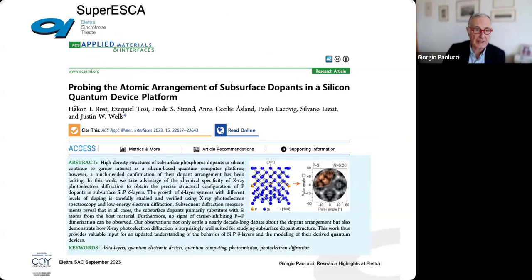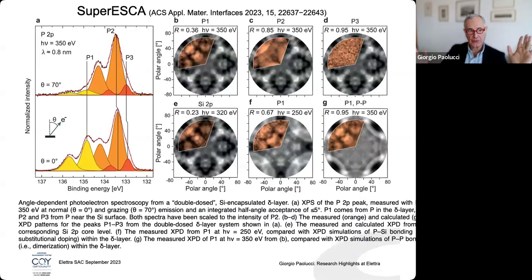This is an example that was measured a few years ago, published in 2023, in which they looked at the atomic arrangement of dopants in silicon. This was done by looking at the angular distribution of photoelectrons. You look at what is below the surface, and by looking at different directions, you get different scattering conditions, and so you can reconstruct what is going on at the surface.